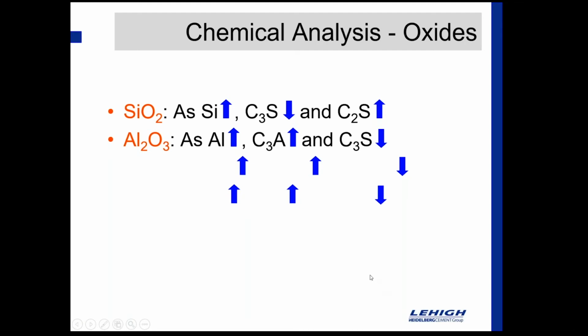If I raise my alumina content, I'm going to raise the C3A. So then I'm going to release a little more heat once the water hits that. My early strengths are probably going to bump up a bit, but I've got a pretty hot cement now. So that means I couldn't have a cement maybe that would go into a mass concrete application. But while I'm raising the C3A, I would also be lowering the C3S. So I'm kind of trading off there. I'm raising some early strength gain with the C3A, but I'm losing some early strength performance by lowering my C3S.